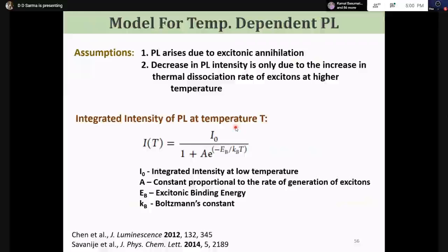One technique of finding out is to look at the photoluminescence coming out. Because what happens is, if an electron and hole are generated and they're coupled by an excitonic binding energy, they will decay. But if you provide enough energy so that the excitonic binding energy is overcome and the electron and hole are decoupled, then they'll move apart, and so the photoluminescence event will not take place. So as I increase the temperature compared to the binding energy, exponentially I excite this excitonic state into the free electron hole state. So the PL emission intensity will have an exponential dependency on temperature, and it will become lower intensity at higher temperature because the excitons are breaking apart.